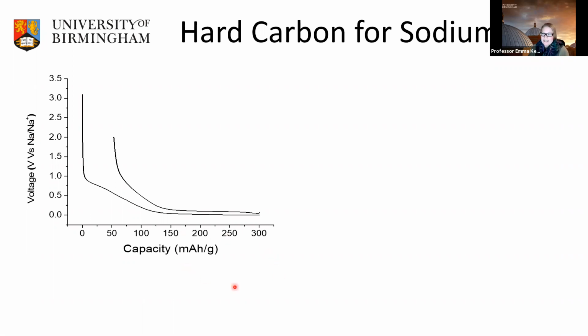Magda's done an awful lot of work looking at optimizing the hard carbons for sodium-ion performance. What we've been doing is trying to optimize the electrodes for performance. Now, it's quite an interesting material because you have a sloping voltage profile here and then a flat voltage profile on the bottom. And in this sloping voltage profile, it's thought that the sodiums intercalate in between turbostratic layers of graphene within the hard carbon structure. And then this flat plateau here is where it's thought that we get pooling of the sodium and we get kind of metallic sodium nanoclusters forming in the vertices of where these turbostratic graphene layers interact.